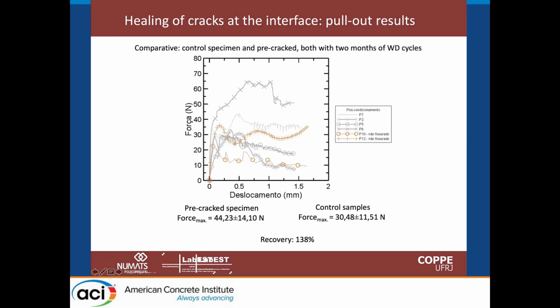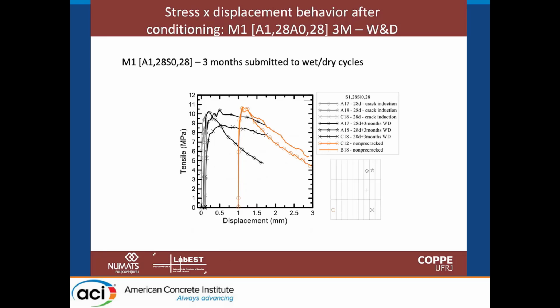And after doing tests in healed and unhealed and uncracked materials, we also can see here that we have nearly the same response. This red material here is a composite that healed. On the other hand, the other material in black here is a material that wasn't cracked. It was only kept under normal cure.